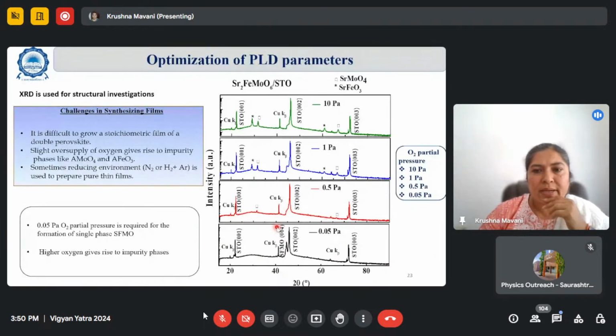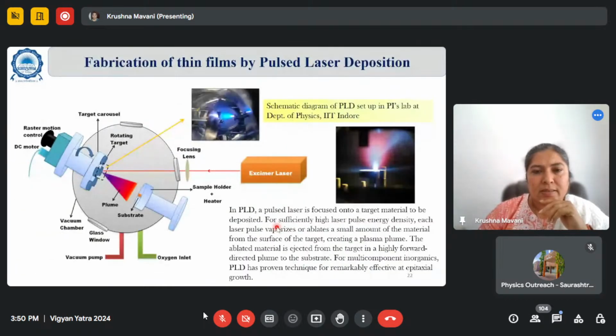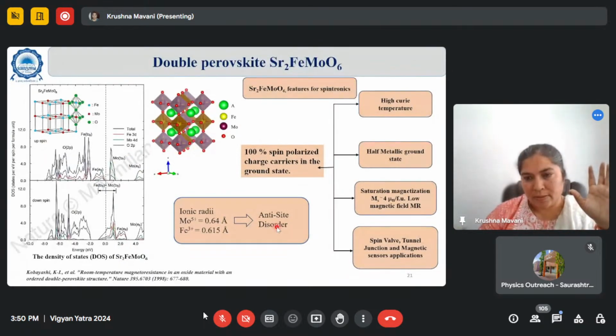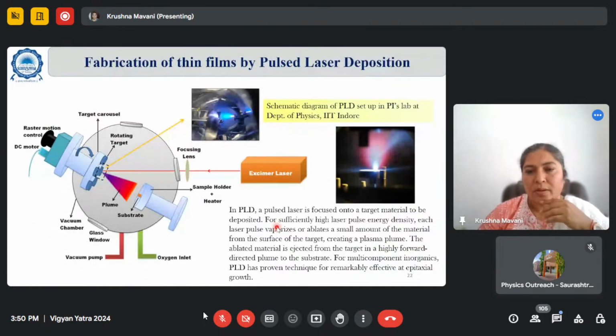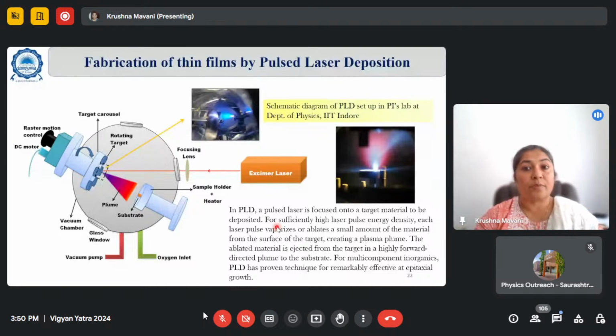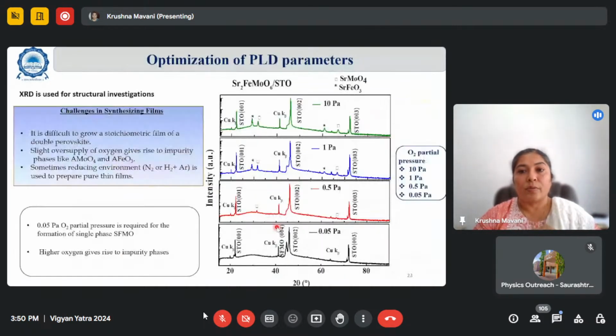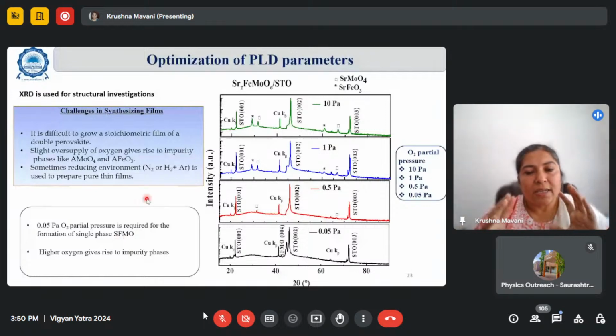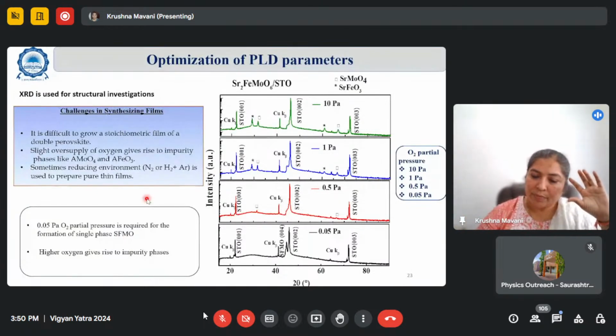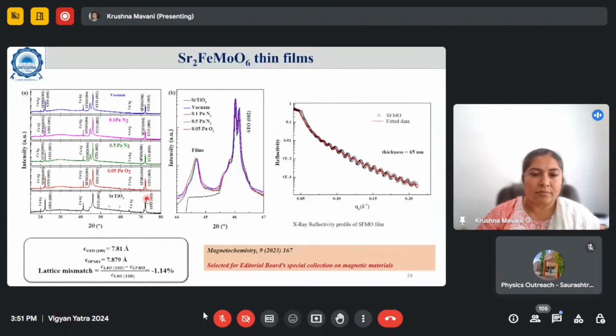Here I would like to show you that when you do thin film deposition, generally thin film deposition of double perovskite is not so easy. Only PLD grown films are shown generally to have half metallic nature and perfect cation ordering. Now one important feature which we observed in our laboratory is that when you vary the background gas pressure from low to high, you can see the impurities coming up. So what we observed is that it is better to have vacuum and deposit the films, so that the film has very high cation ordering at the B site.